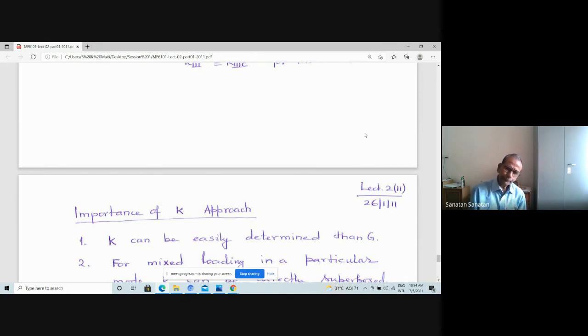You see, stress analysis you have studied all through your life, and you know the concepts very easily. Here, in the case of fracture-based design, it is again the stress field which is important in designing a component, or in specifying the failure condition of a material. So the stress field around the crack tip had to be analyzed, and it was analyzed, and finally it was found that the stress field has a typicality, that it is a field having a series of terms.